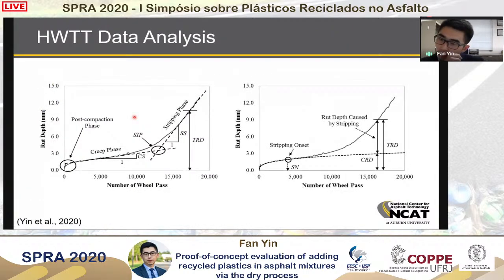In terms of Hamburg analysis, I'm showing the two approaches that we have been using. On the left side is the traditional way, where we look at the total rut depth and the stripping inflection point. On the right side, we look at the alternative approach so that we can separate the rut depth caused by rutting versus the rut depth caused by stripping. In this case, we are using a corrected rut depth and stripping number as the parameters.